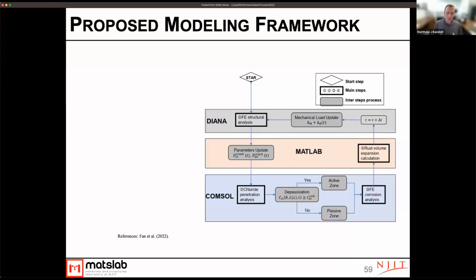And basically that requires some input parameters, such as chloride diffusion coefficients, that we took from our experimental testing. And then based on the chloride diffusion that we have, we can then figure out, has depassivation occurred? If so, are we going to go into a corrosion analysis? And then that corrosion analysis, when corrosion products form, those products cause volume expansion, which then leads to cracking.